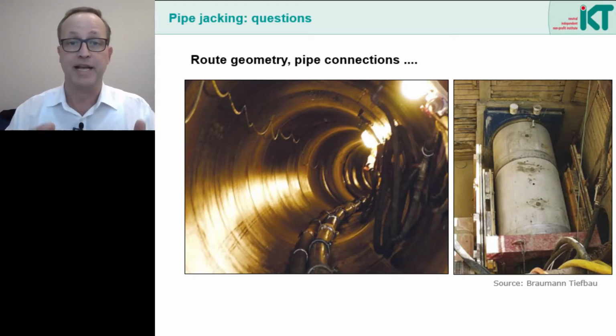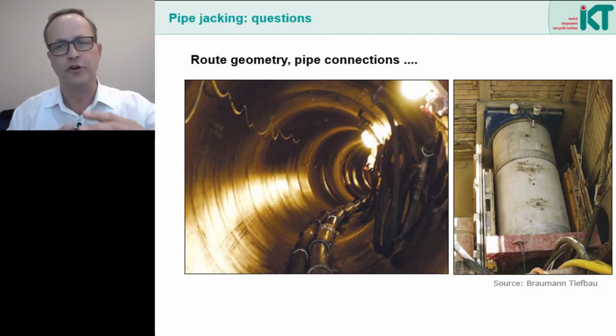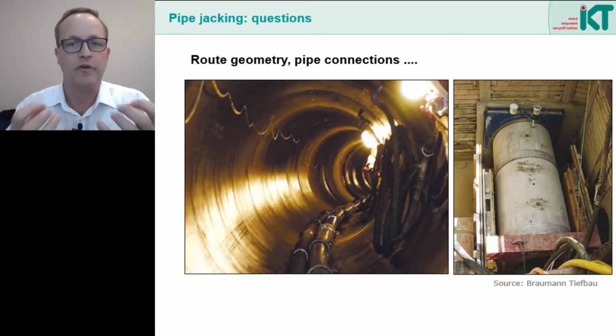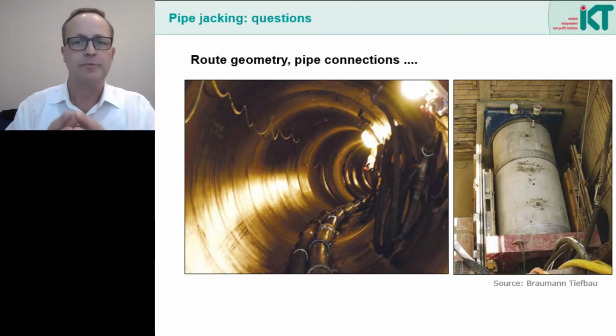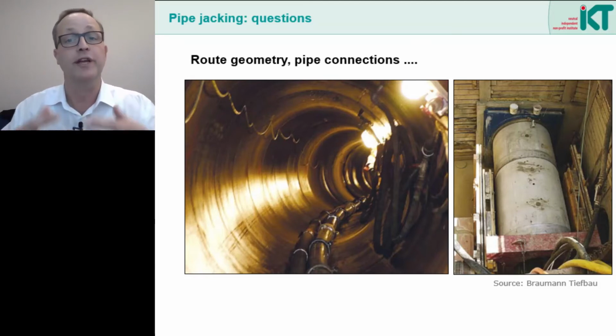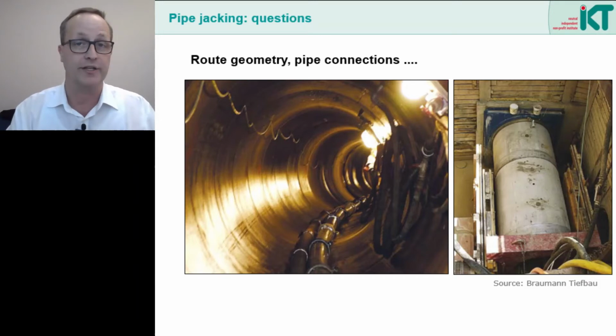The pipes themselves usually cannot be bent around the curve. A jacking pipe should absorb jacking forces and therefore it is usually very stiff. Large pipes, for example, are usually made of reinforced concrete, so if the pipe is to be bent around a curve, all bends must be made in the pipe joint.